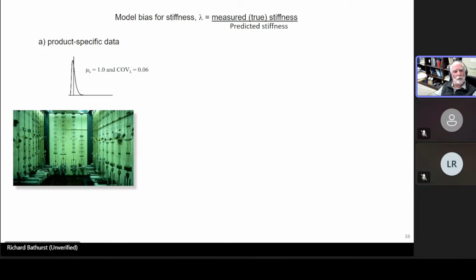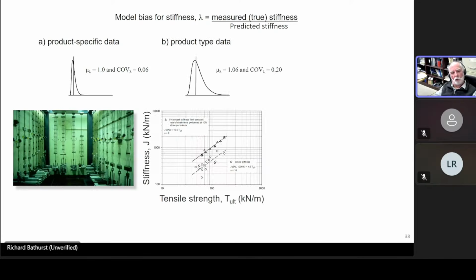And if you gather that data, the mean of your predicted values and your measured values is about 1. And the spread, the coefficient of variation, is about 6%. If, however, I use this correlation between tensile strength that I showed you before and the stiffness, so that from my nominal value of tensile strength, I estimate what the stiffness is going to be, there's some scatter. And from collecting data from products from the same product line, the spread is about 20% on your estimate of the stiffness.